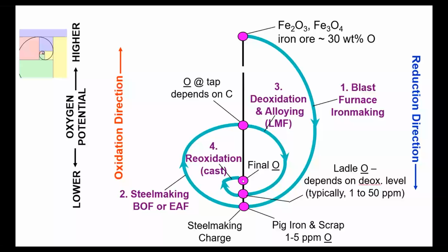And then because none of us are perfect, we end up with some reoxidation when we go to the caster, whether you pick it up from siphoning in air as you're transporting steel from a ladle to a tundish, from a tundish to some type of mold. You pick up oxygen along the way and end up at a final oxygen content.